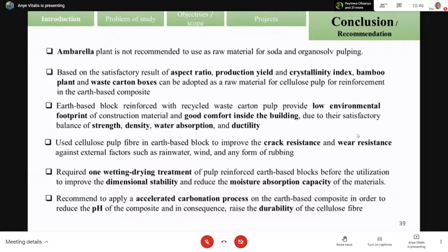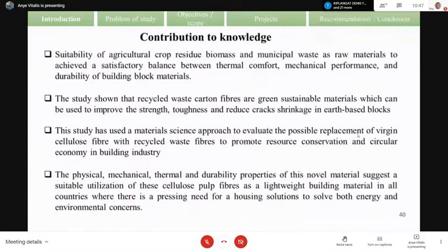We recommend also using the accelerated carbonation process, which will help us to reduce the pH of the material, which can help to raise the durability of the cellulose fiber with time. So what is the contribution to knowledge? The suitability of agricultural crop residual biomass and municipal waste as a raw material to achieve a satisfied balance between thermal comfort, mechanical performance, and durability of building block.